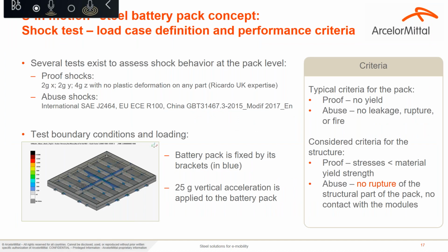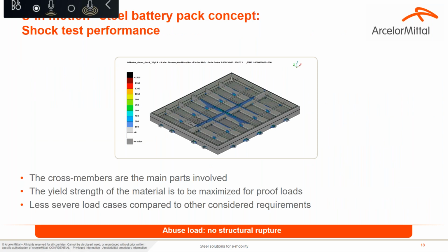Shock tests. You have several types of shock tests: proof shock, where you don't want to deform the structure, or abuse tests, where you don't want to have a rupture. In our case, we tested all of this, and we show you only the most difficult one, the 25G vertical acceleration on the 320 kilograms of cells in the middle of the pack. And we succeeded to have low strains in this case. So this is not the most difficult test to pass. But for the proof test, where you don't want deformation, you also need to stay in the elastic range. So you need a high yield strength of this material.